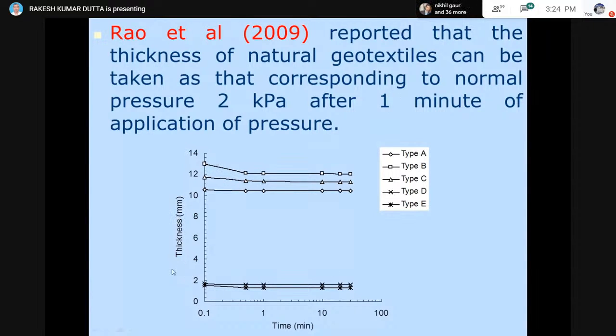Based on this study, I am showing you this diagram. On the y-axis, the thickness is there. On the x-axis, we have shown the time in minutes. Here I am showing type A, type B, type C, type D, type E. These are all combinations of woven and non-woven types of geotextiles. The thickness of all these materials was measured under a pressure of 2 kPa. If you see, at a time of about 1 minute, beyond this there is not much change in the thickness of this material.